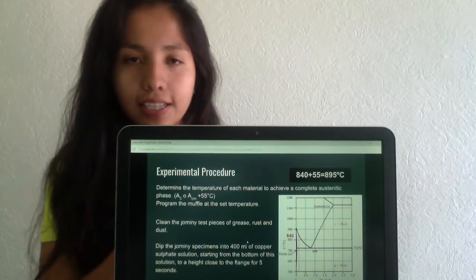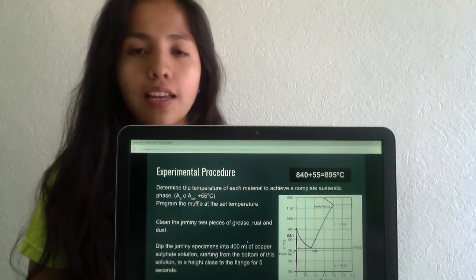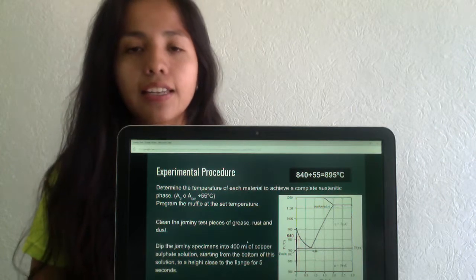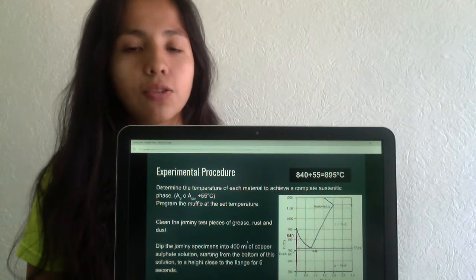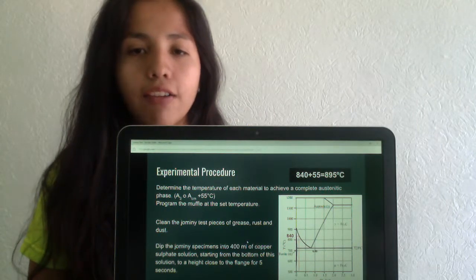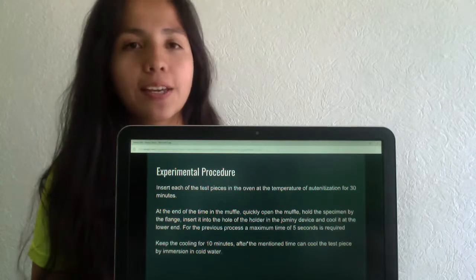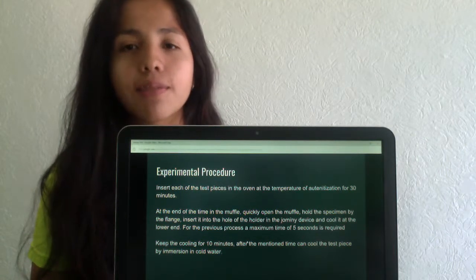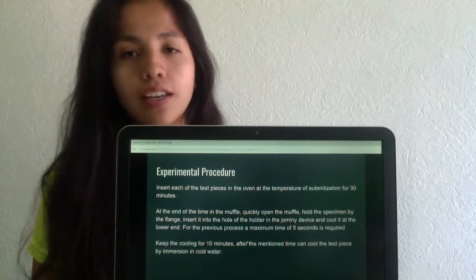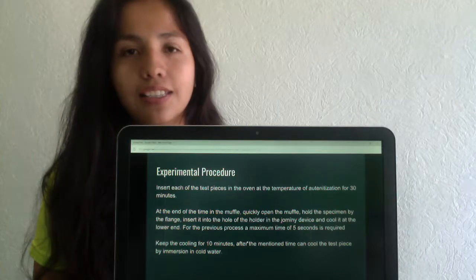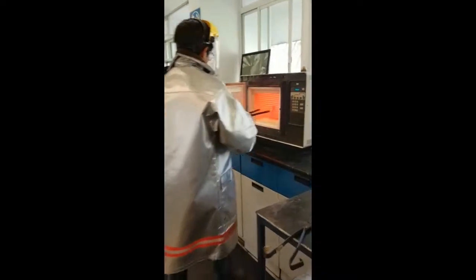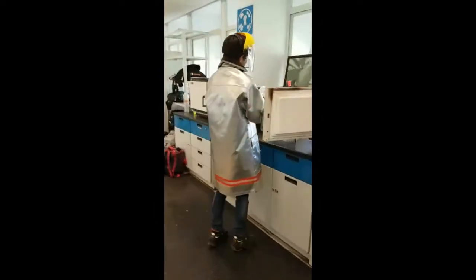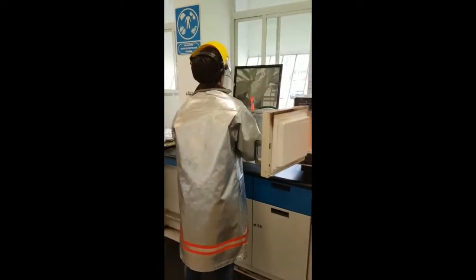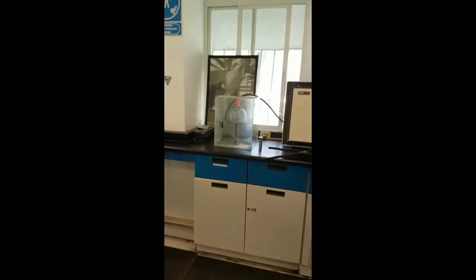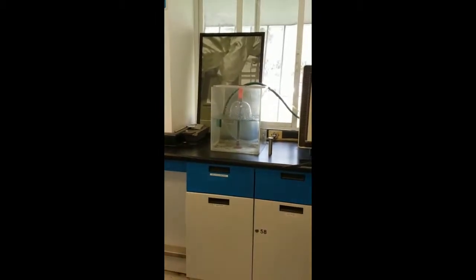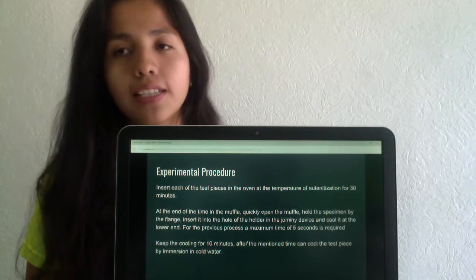Then we clean the Jominy test specimen of grease, rust, and dust, and introduce it in copper sulfate solution for 5 seconds. Then we put the specimen in the muffle for 30 minutes, at the temperature of austenitization. Then we open the muffle, hold the specimen and introduce it in the Jominy device. This needs to be done in less than 5 seconds. And we rest the specimen here for 10 minutes and then cool the piece in cold water.